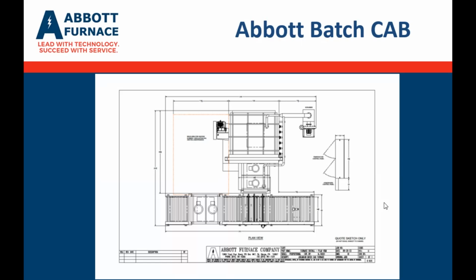As we hit braze temperature, we soak for 2 to 3 minutes, whatever the process calls for. Then that inner door opens back up and the part comes back out. Now, instead of acting as a purging chamber, that chamber is acting as a cooling chamber. So it is a multi-use chamber, which gives us a smaller footprint. After the part is cool, it can come back out onto the material handling section of rollers and then be transferred to the left. And you see just a final air blast where you're utilizing your plant air to put a high volume of air through the load to cool the parts down for manual handling, fixture removal, any kind of testing or painting that may need to be done.